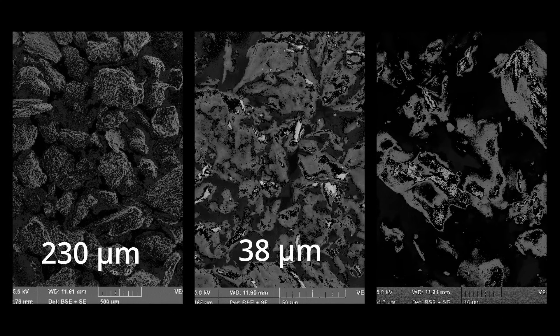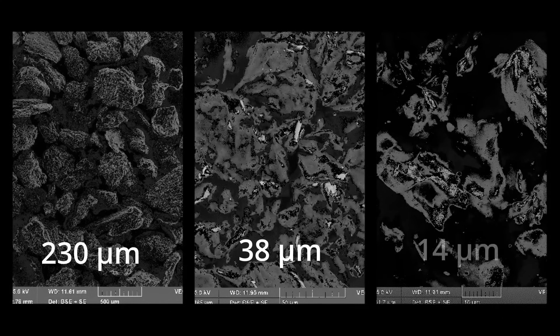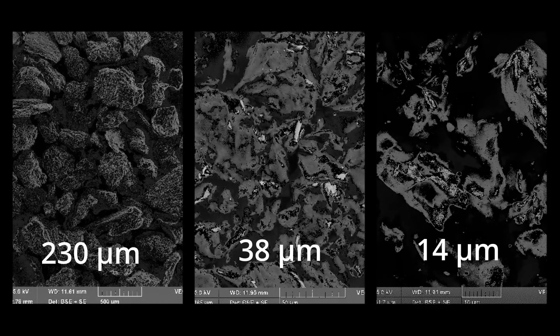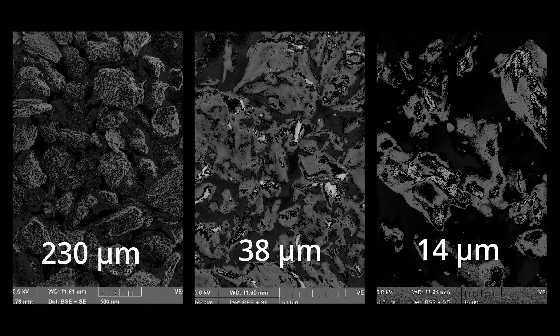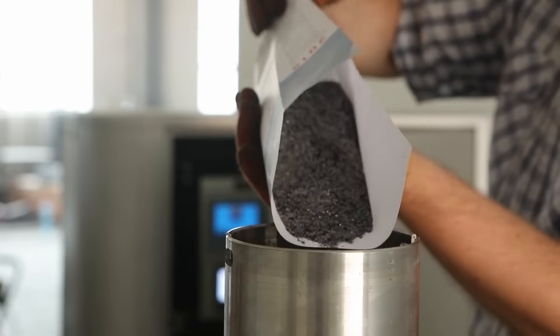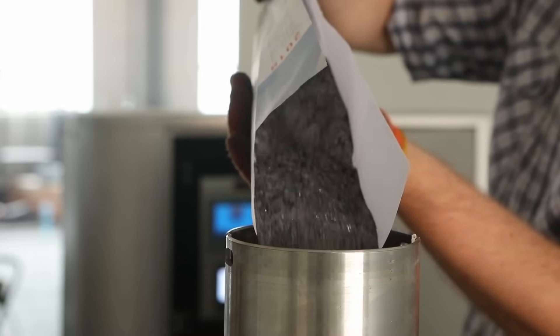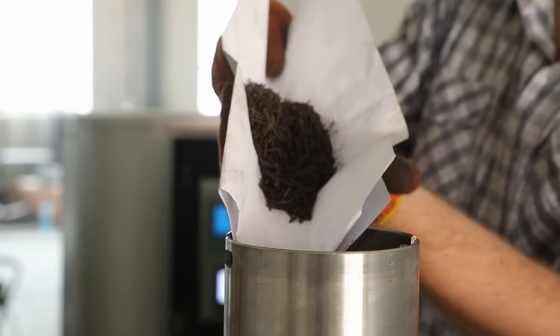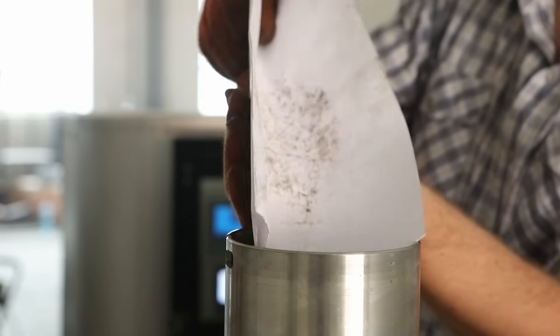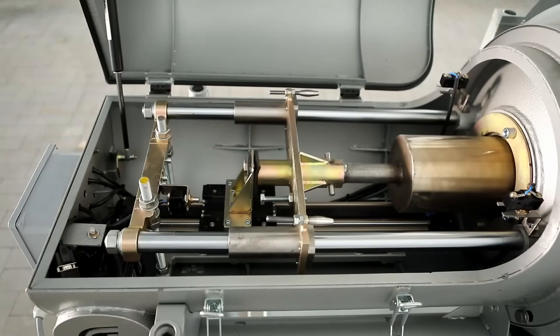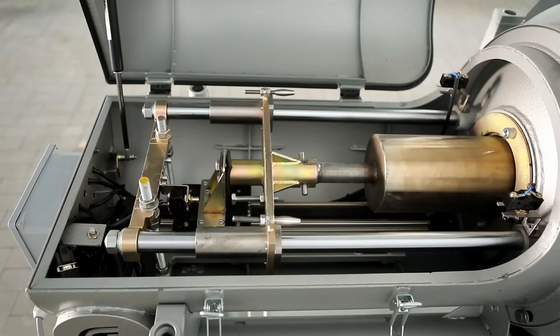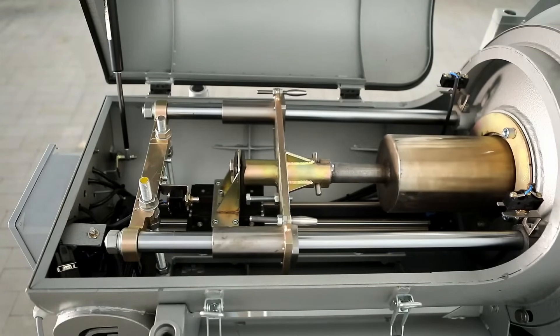We used 1.8 kilograms of graphite and 500 grams of steel ferromagnetic particles for dry milling. Milling in the vortex layer of the graphite milling machine AVSP150 was carried out for 30 and 60 minutes. You can see the granulometric distribution of particles in the initial and milled samples on the screen now.